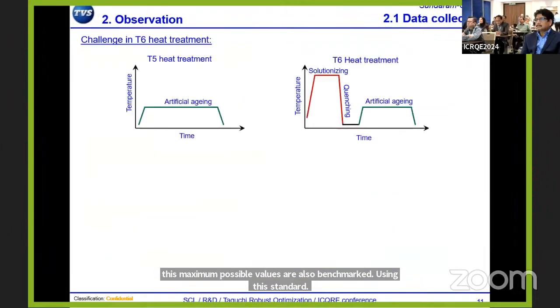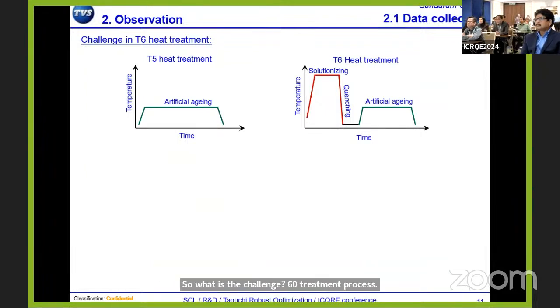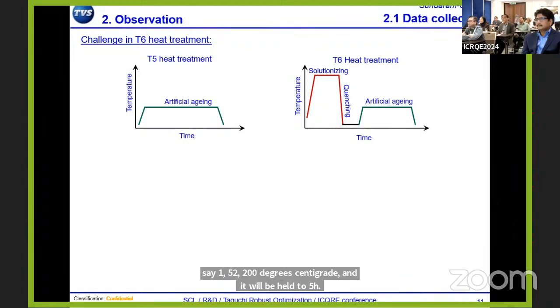So what is the challenge in the T6 heat treatment process? If you see the process difference between T5 and T6, T5 heat treatment is the one where the castings are heated to a lower temperature, say 150 to 200 degrees centigrade, and held for 2-5 hours. Whereas the T6 heat treatment process has 3 steps: solutionizing, then quenching, followed by artificial aging.